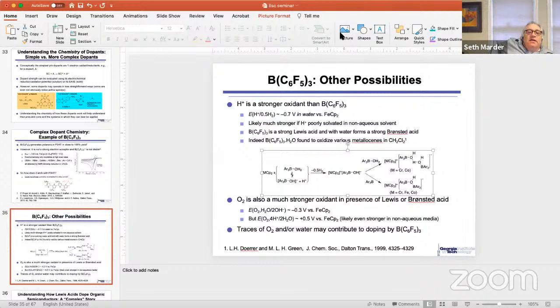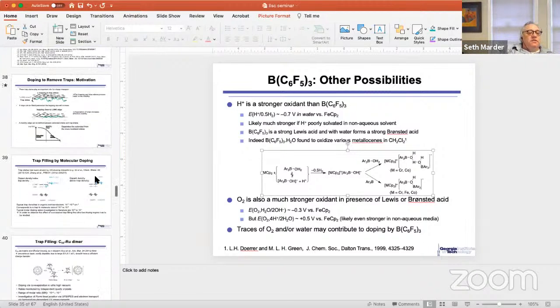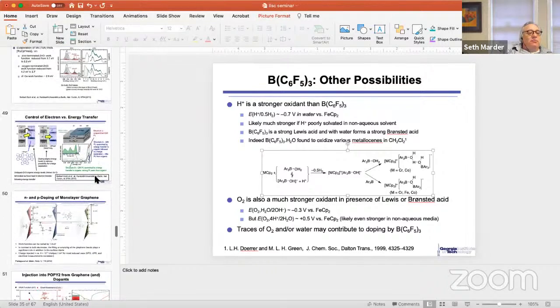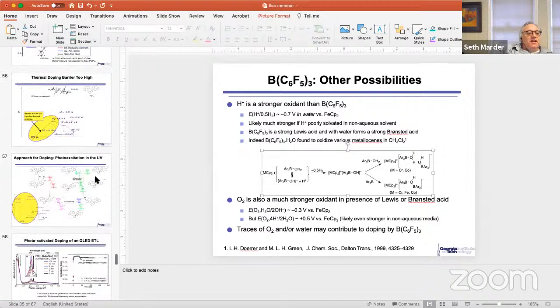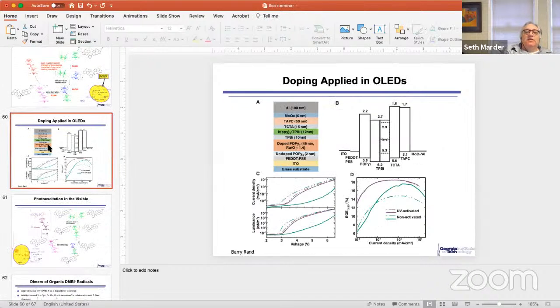So that's one thing. The other thing is that while I didn't get into it, I'm absolutely certain that when Barry Rand put this device structure together that I showed here, which has 18 jillion layers, okay, by and large he put in things like this 10 nanometers of the TPBi between the iridium dope layer and the dope layer, probably to manage exciton diffusion and things like that, okay? So that you didn't have the doped layer in direct contact with the emissive layer, okay?